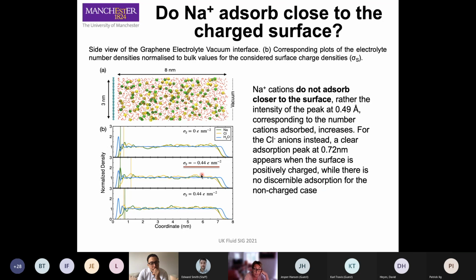Then what we did, we charged the surface. We charge with a voltage, a negative and a positive voltage. And we expected ions this time to dehydrate, but instead what we found, so if you look at what happens when you negatively charge the graphene, we expected sodium to dehydrate and enter into the Helmholtz layer, but instead it doesn't. What it does is that there is a higher concentration of sodium near the surface compared to when it's uncharged, but it doesn't dehydrate. Chloride, as you expect, moves much further away from the surface. When the surface is positively charged, chloride still stays quite far, and as you expect, the cation is repelled. So basically the result here is that sodium doesn't dehydrate and absorb with a total dehydration. However, it's still within a very small distance from the surface. So it is probably within the Helmholtz layer, but it doesn't dehydrate.